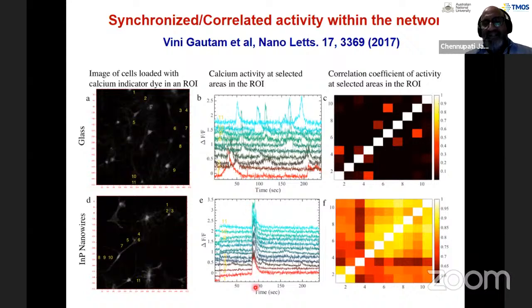They're all firing at the same time. You see excellent correlation, indicating that we got some sort of synchronized and correlated activities taking place on the neuronal network which we've grown on these indium phosphide nanowires. And Vinay Gautam presented this work at a neuroscience conference a couple of years back.